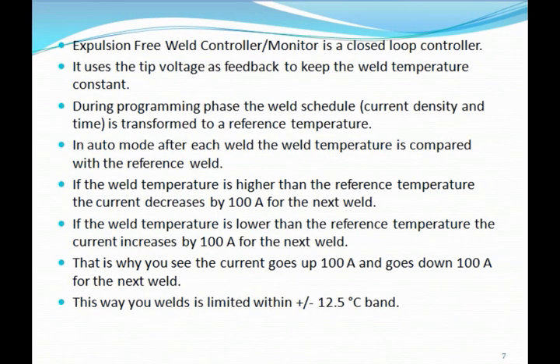Expulsion-free weld controller/monitor is a closed-loop controller. It uses the tip voltage as feedback to keep the weld temperature constant. During the programming phase the weld schedule, current density and time, is transformed to a reference temperature. In auto mode, after each weld the weld temperature is compared with the reference. If the weld temperature is higher than the reference temperature the current decreases by 100 amperes for the next weld. If it is lower, the current increases by 100 amperes for the next weld. That is why you see the current go up 100 amperes and down 100 amperes for the next weld. This way the weld is limited within a ±12.5 degrees Celsius band.